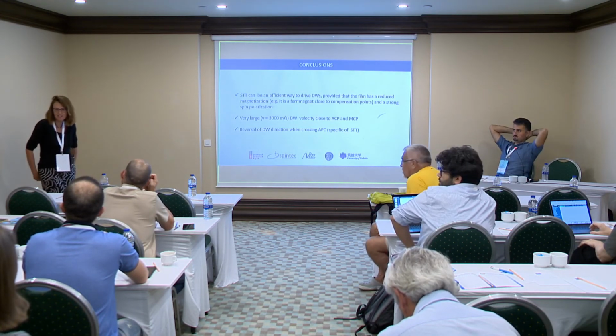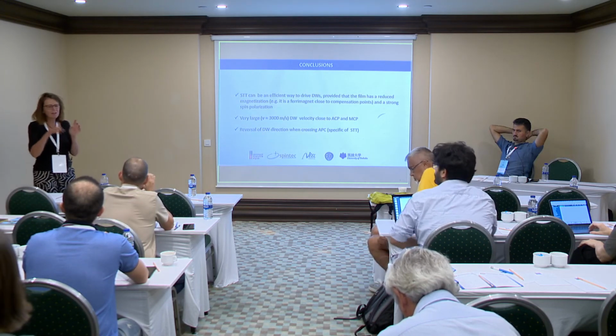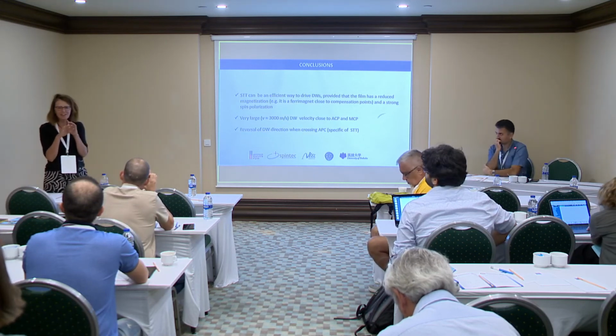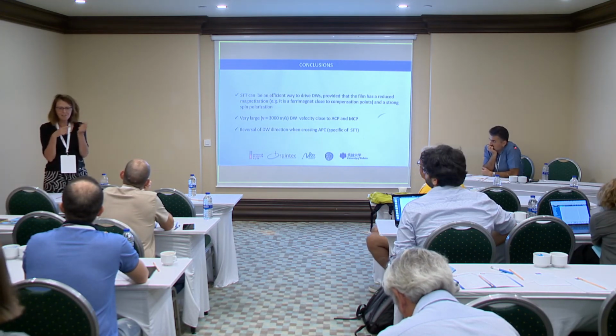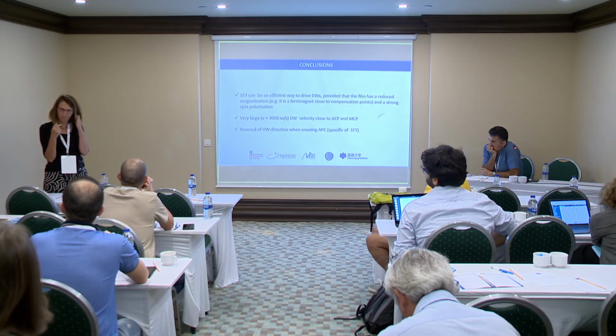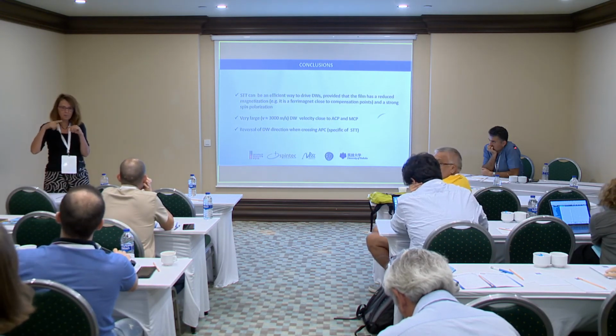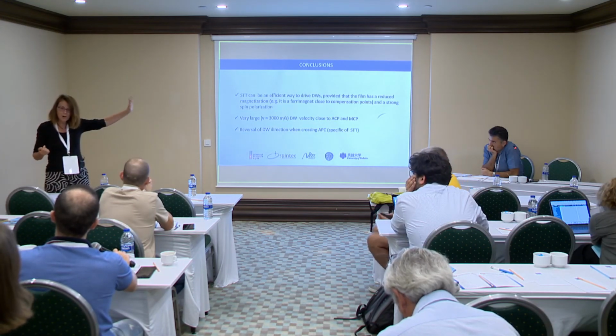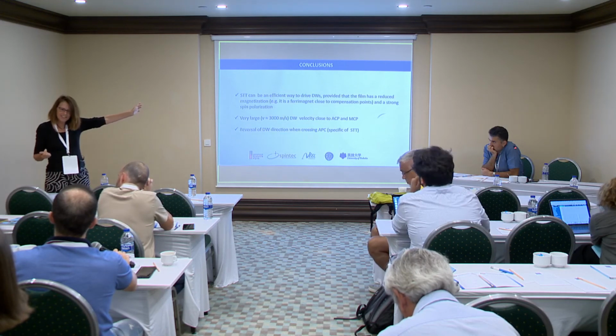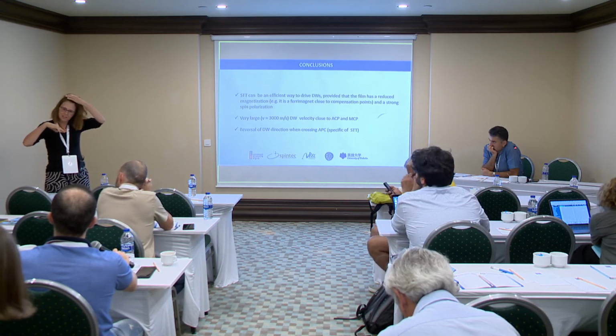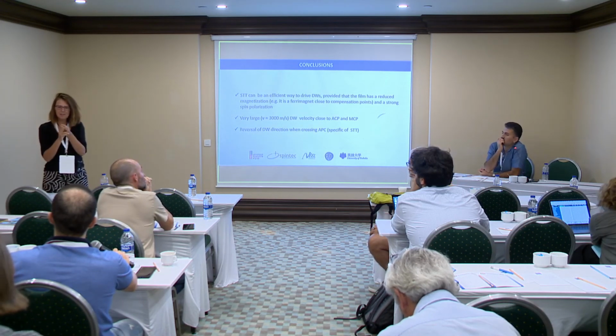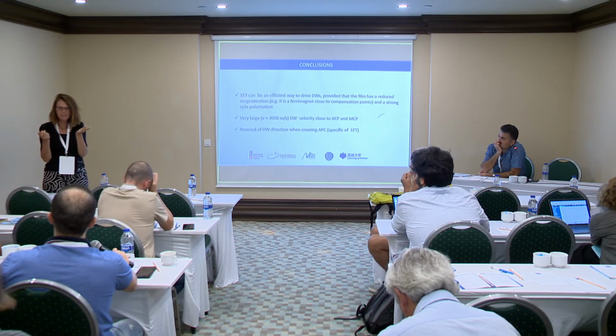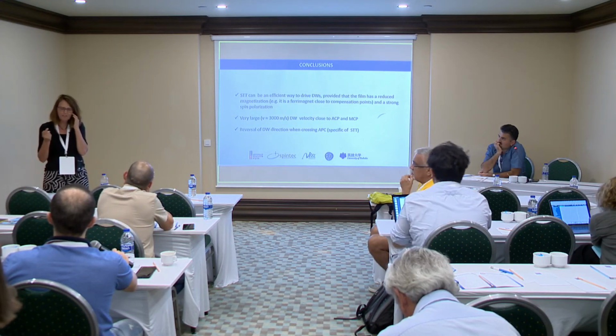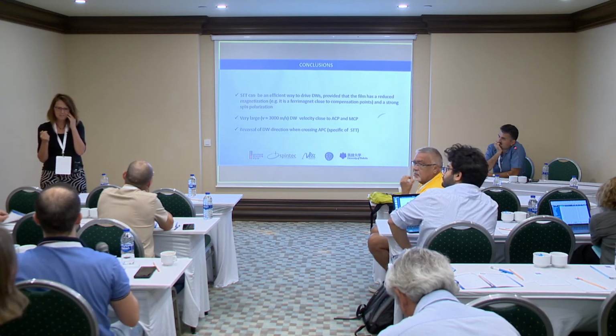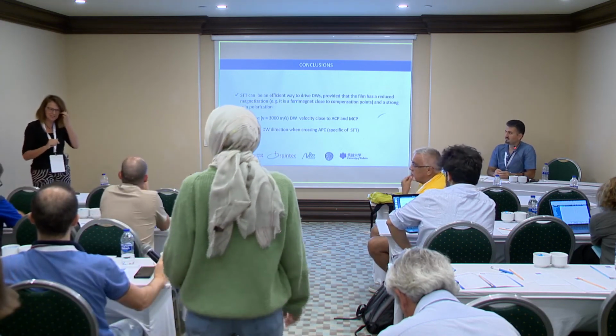The Walker breakdown is actually relevant, but there are two regimes. Here we are in a regime that is beyond the Walker breakdown. The breakdown in these systems is very low, because the Walker breakdown corresponds to the field at which you start the precession regime, and we are already beyond it. It is determined by the demagnetizing energy of the domain walls, which is extremely small in the sample because Ms is practically zero. So this is beyond the Walker breakdown. Everything is in our first paper, Nano Letters 2020.